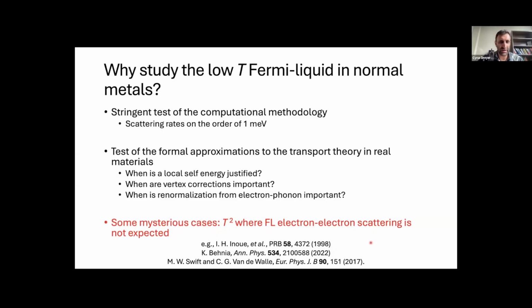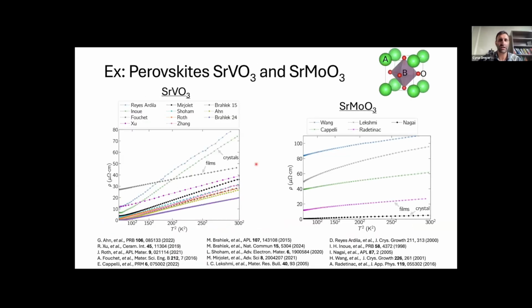So I'll show an example of this, and this will be kind of the topic or the through line of the talk. It's in two very simple materials that I think are probably known to many of you. They're perovskite oxides, strontium vanadate and strontium molybdate, both cubic, at least at high temperatures. So they're quite simple materials. And the interesting thing is that if you plot the resistivity versus T squared, you see basically straight lines. So these are a bunch of collected experimental data. And so these materials show a T squared scaling of the resistivity up to very high temperatures, including room temperature.